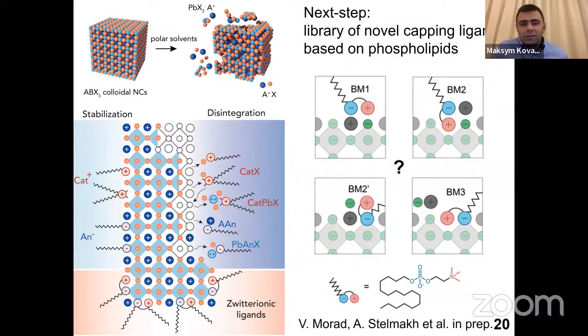Most nanocrystals, cadmium selenide, gold, nearly everything, bind to ligands through covalent bonds. Thiols, for example, on the surface of gold attach very strongly because of the very strong sulfur-gold bond. Oleate on the surface of cadmium selenide attaches through a rather strong carboxylate-cadmium bond. Perovskites are very soft ionic species. So you cannot play with the covalent attachment of ligands here, because if you attach something covalently like thiols, you will actually destroy the nanocrystal, because the binding of your ligand to your ion will be much stronger than between the ions inside the lattice. So you've got to deal with these ionic surfaces in a smarter way than covalent attachment.